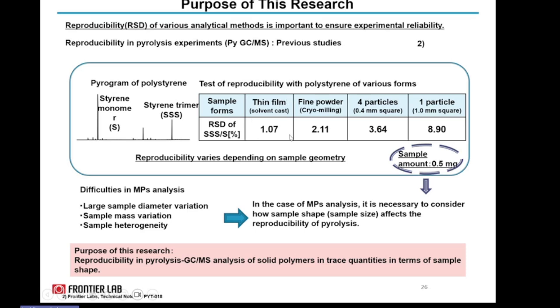So in solvent form, you are getting the best reproducibility, as expected. Whereas when you use different particle sizes, from fine powder to particles of different diameter, then your RSD really varies. So this is one thing that tells it's important to use a cryomill to really powder your sample before the analysis.